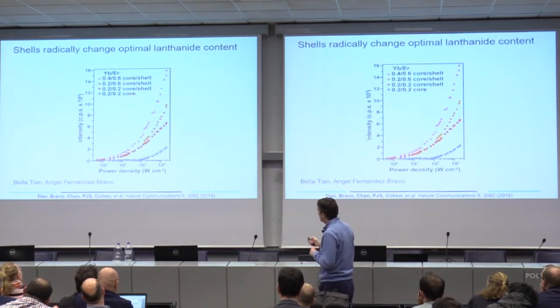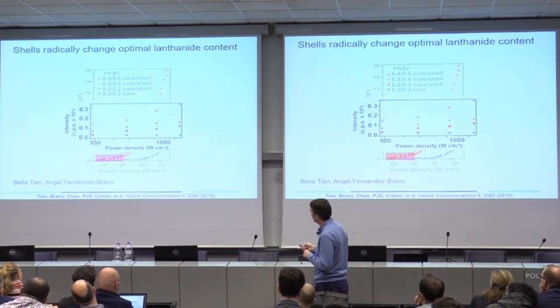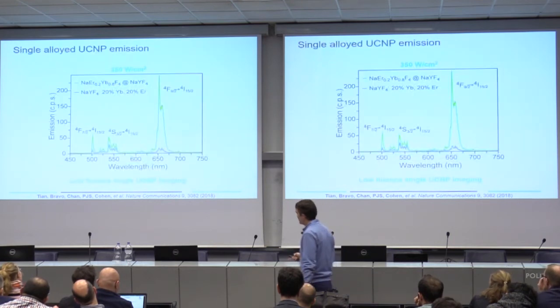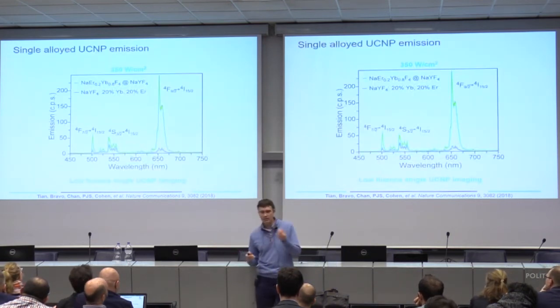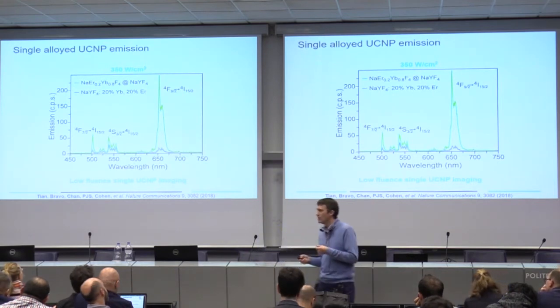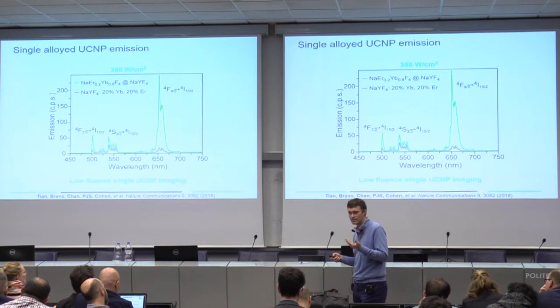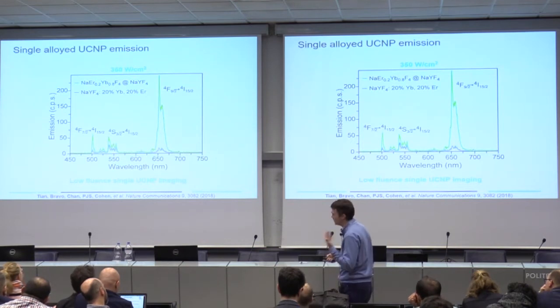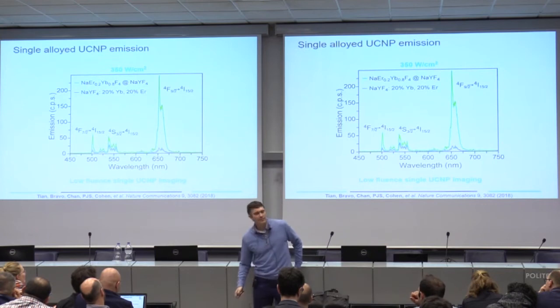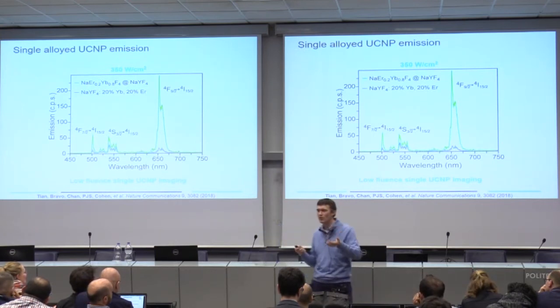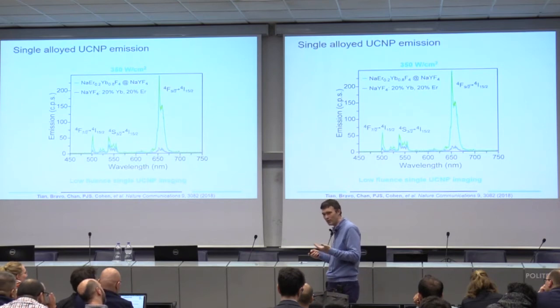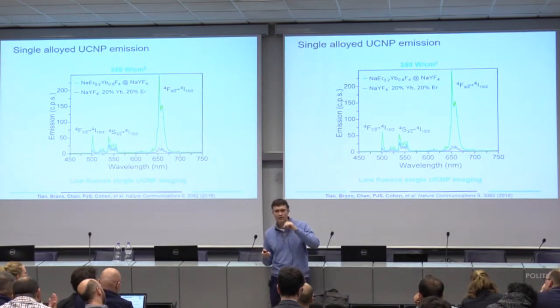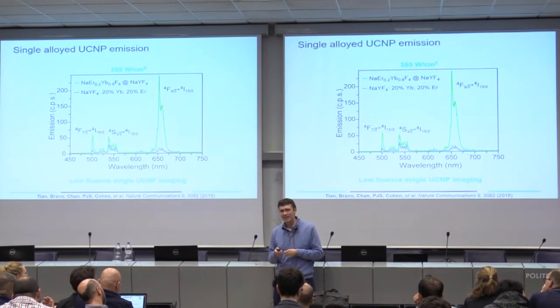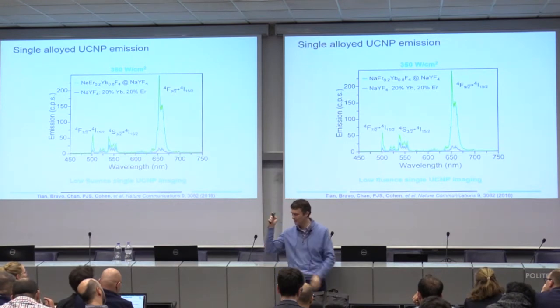And in fact, they get bright not only at high pump powers, but they're actually brighter at all powers. Even down at low power, you can see that these compositions are the best. And in fact, what this means is that now we can even image single particles, sub-10 nanometer particles, with 2 orders of magnitude lower pump power than we had seen before. So this is at a density of 350 watts per square centimeter. So what is that? That's 2 or 3 orders of magnitude better than what we were seeing before. But to give you a little perspective, I think for humans, the FDA allows you to put in a little less than a watt per square centimeter into human skin at 980.